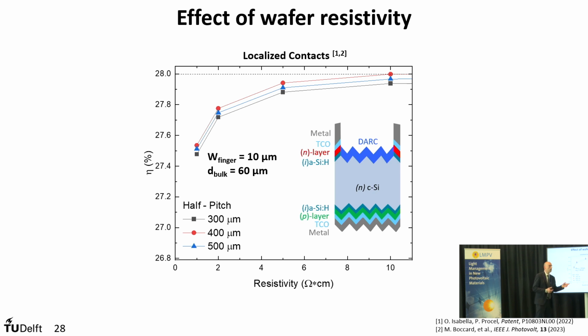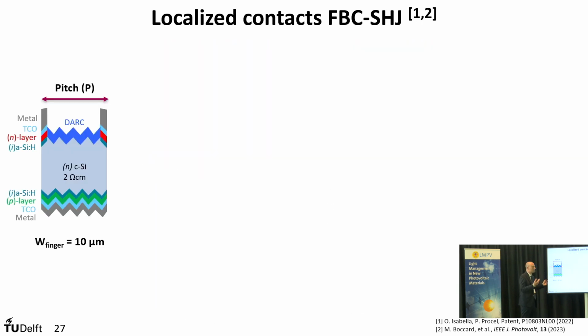In case of an N-type stack, if you remember, maybe I can go back a couple of slides. Okay, so it's many slides. If you remember the N-type side, you have a direct tunneling through the N layer and the TCO, and afterwards you get directly to the metal. So with the N-type, you can afford to not use it, but then your N-type material must be a little bit more conductive and also relatively thin in order to not lose too much in this transfer process. So it depends. And related to this, because your back contact is also a reflector, it's the combination of transparency and electrical conduction that all together you need to optimize.